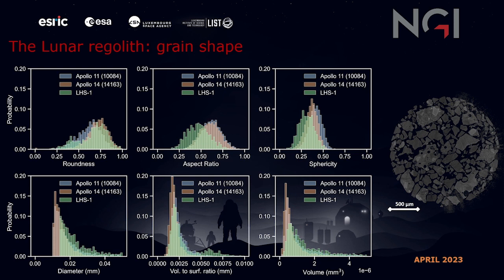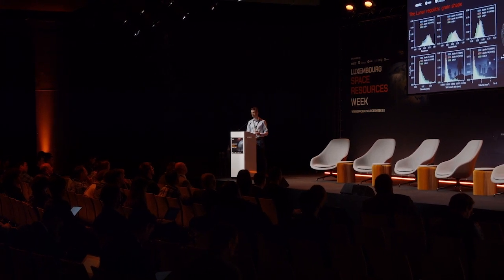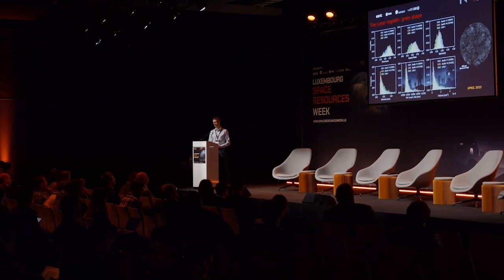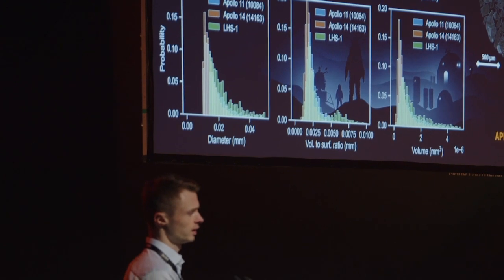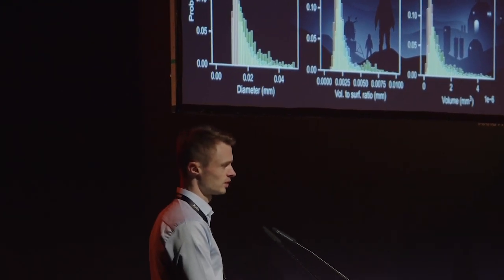So it actually means that the LHS simulants are kind of longer and thinner, relatively speaking, than the Apollo samples are. And this may be due to how it's been made compared to the formation of these particles on the moon. So it's through breaking and crushing of grains, so we might end up with more elongated features. Whereas on the moon, you have these agglutinates, you have melting, solidifying. So yeah, different processes may mean that we have these different shapes.